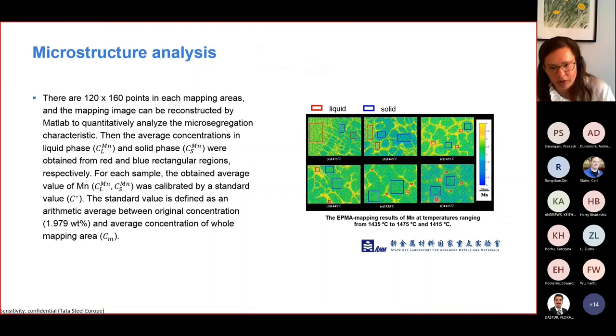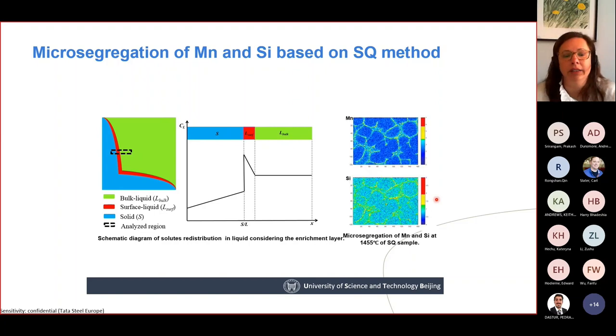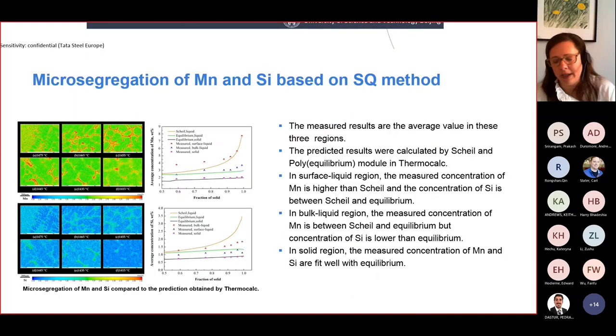If we combine that, and we use again the same samples, and we go to an EPMA and map it, and then we try to understand the segregation of the different elements, in this case manganese and silicon, we could get even more information. Knowing, for example, for a simplified phase field approach, that there is between the solid and the liquid an interface, and this is a very important concept for phase field, it could have a different segregation. So if we follow these two, manganese and silicon, excuse me,